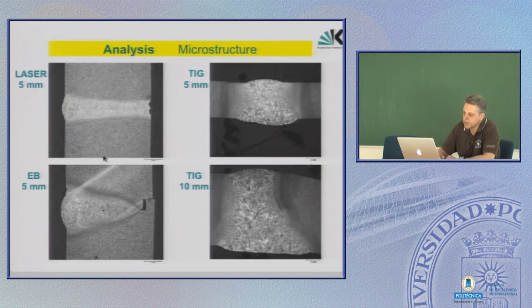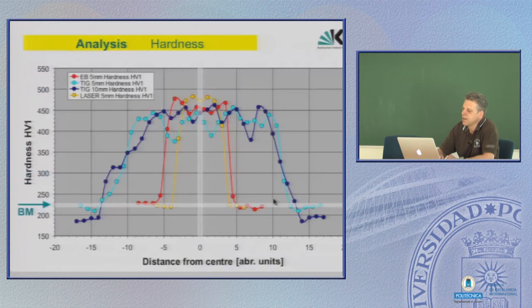The same is here with the beam weld, of course, but the so-called heat affected zone, where the transformation was not unique or perfect, is smaller compared to the tungsten inert gas welds. You see it also here in the hardness profile. At the end here, this is the base material property from Eurofer in terms of hardness.